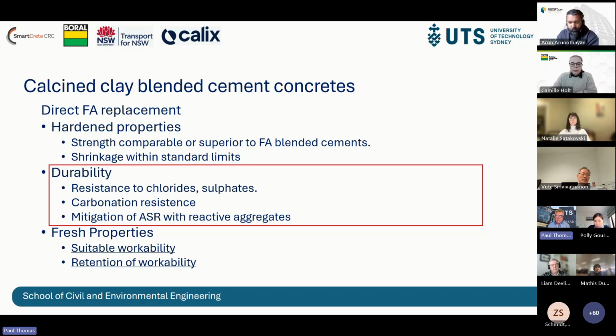Fly ash is not particularly resistant to chloride, so we might not expect calcined clay to be either. The carbonation resistance is probably not too good for fly ash either, so if we do better than fly ash, we're on to a winner. And what fly ash is really good at is mitigation of ASR, so we need to address that with calcined clay.